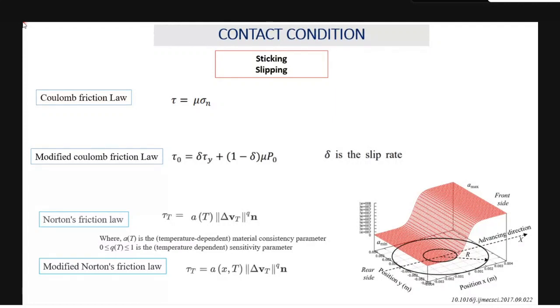Friction is the main phenomenon during the slipping conditions. And when you have friction, the heat generation is mainly contributed by the friction. In sticking, the material is moving along with the tool, where the velocity of the material and the angular velocity of the tool are similar. In that case, the plastic deformation plays a major role in heat generation. In the partial sticking and slipping condition, you will have both, where the heat generation is contributed by the friction as well as the plastic deformation. So these are the three basic contact conditions, and with different friction models, we are going to achieve these kinds of conditions.